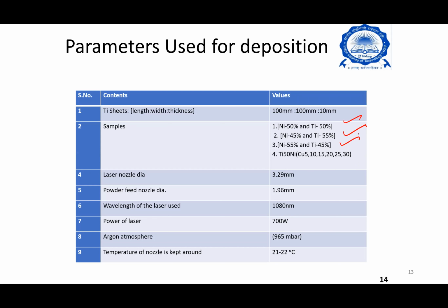In addition to this, since our main motto is to have actuation, we should have some kind of ductility. So we went for a ternary composition, in which we mixed NiTi, Cu, etc. In order to optimize the process, a number of tracks were deposited at different process parameters. After deposition, the tracks were examined and the uniform track was analyzed.